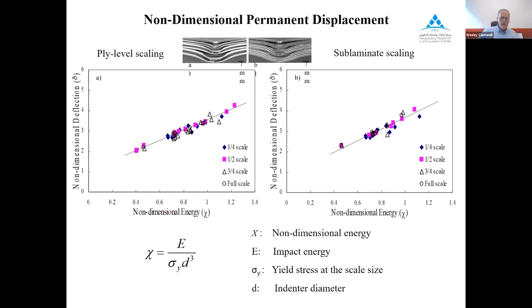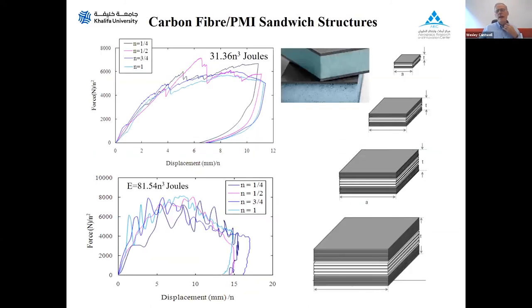Now, Norman Jones, in his impact engineering paper, developed a dimensionless impact energy, and it's shown there. It's based on the actual impact energy in joules, the yield stress at that particular scale size of sample, as well as the indenter diameter. We used that type of non-dimensional impact energy and plotted our non-dimensional deflections against that. And for all four scale sizes, ply level scaling, you see that they fit nicely on one figure there. And also for the sublaminate scaling, which I haven't said very much about, also a reasonably good fit there. So all in all, it seems to work really quite well for these relatively complex hybrid materials, these FMLs.